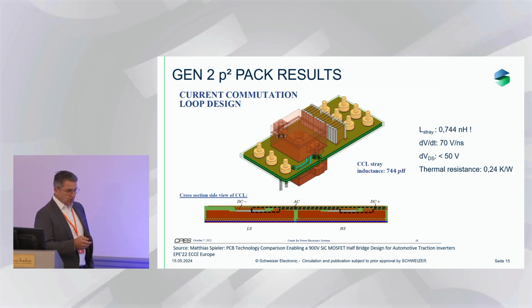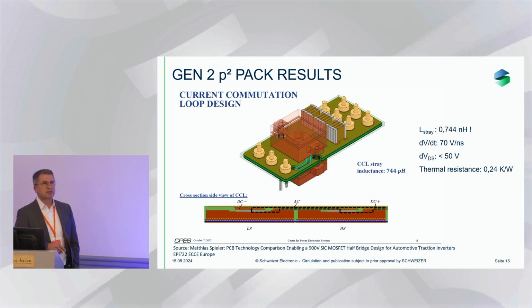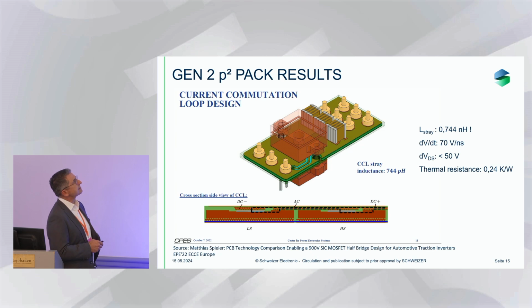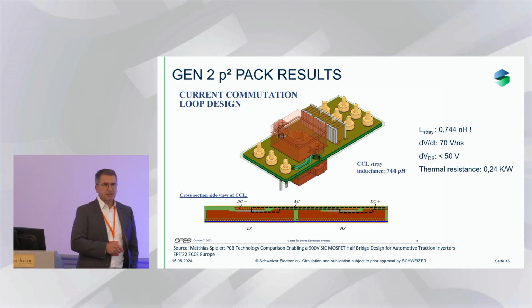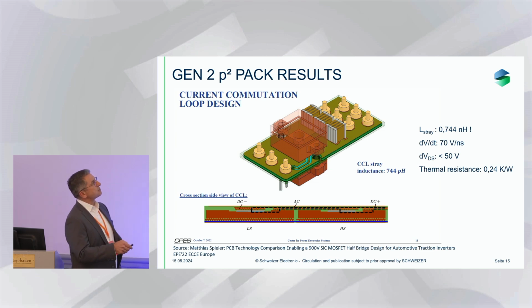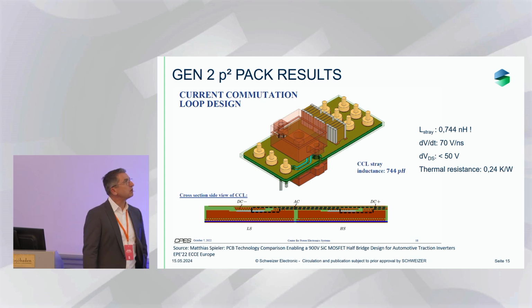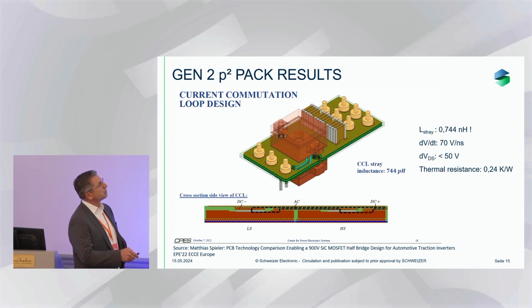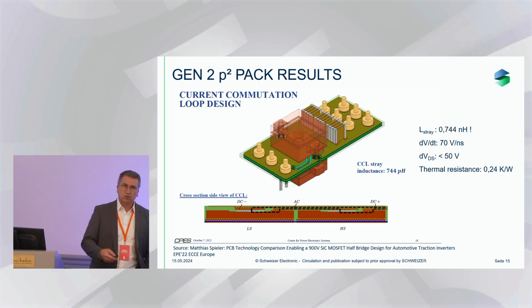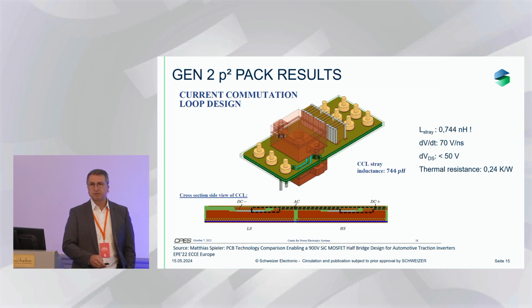So we have been talking about double-sided cooling. We already did one of the applications for one of our development partners, Virginia Tech in the US, where we used double-sided cooling. Due to the double-sided cooling, the thermal resistance went down to 0.24 kelvins per watt. But what is a very nice result is that the stray inductance in this sample was less than 1 nanohenry. It's 0.744 nanohenries. And we could switch very, very fast with 70 volts per nanosecond. And while switching this fast, the overshoot voltage was very little. It was less than 50 volts.